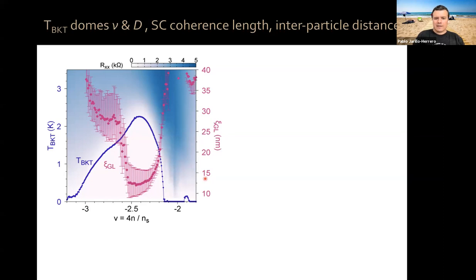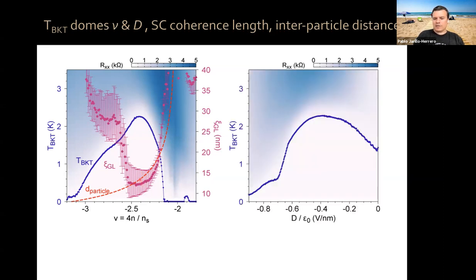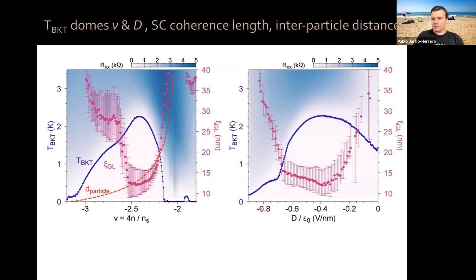In fact, if I show you here what's the average interparticle distance for the system, you can see that the Ginzburg-Landau superconducting coherence length in this underdoped region and optimal doping is very much bounded by this interparticle distance, okay? We can do the same thing at optimal density as a function of displacement field, okay? We can also look at the superconducting coherence length. This is the average interparticle distance at optimal density, and you can see the same thing, okay?